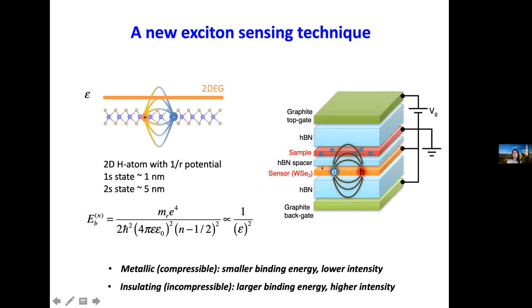So we put a monolayer of tungsten selenide, the exciton in this material as sensor, about a nanometer away from the Moire superlattice. So the spacer kills any direct electronic coupling between sensor and the sample, but is still relatively small compared to the Bohr radius. So you get a sensitivity. And we chose this material such that the optical response of different layers, sample and sensor, is separate into different energies, so you can separate them.